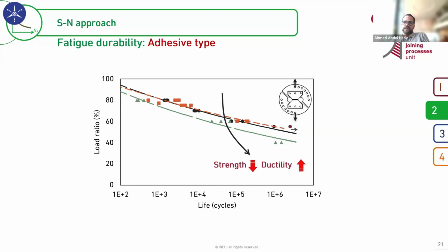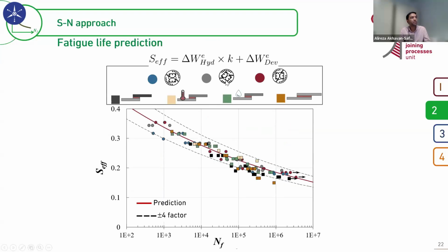Another question is, how can this SN curve be applied if the joint is exposed to different temperatures in real life? Yeah, it highly depends on the parameter that you select as effective. Here, for example, we have this parameter that can take into account the effect of temperature as well. It means that when we change the temperature, we are changing the behavior of the material. It's like testing another adhesive, you know.